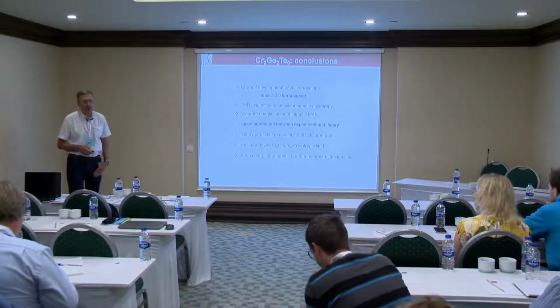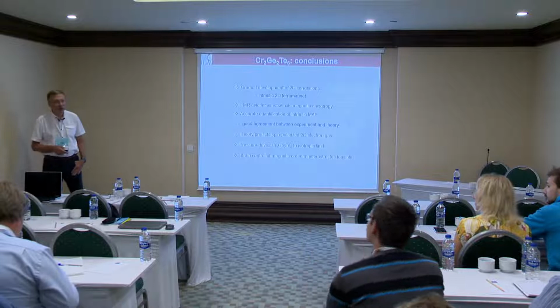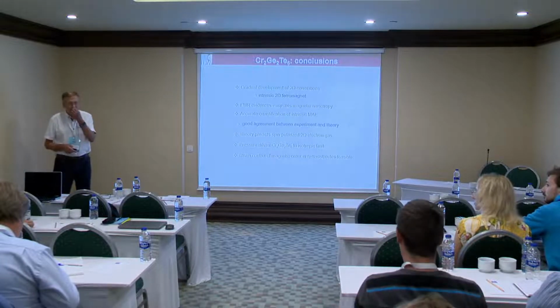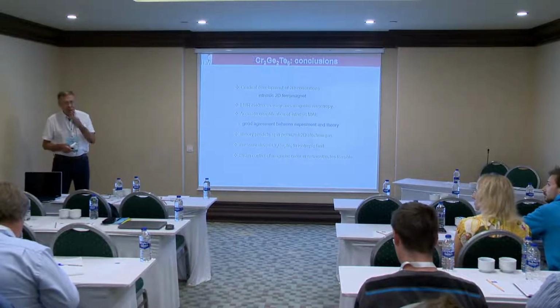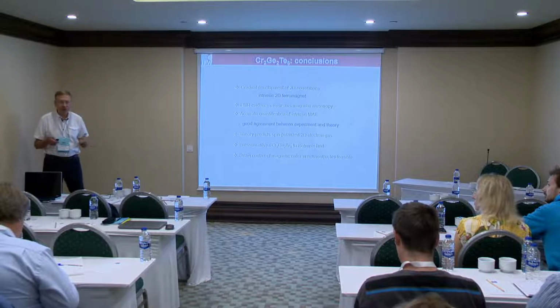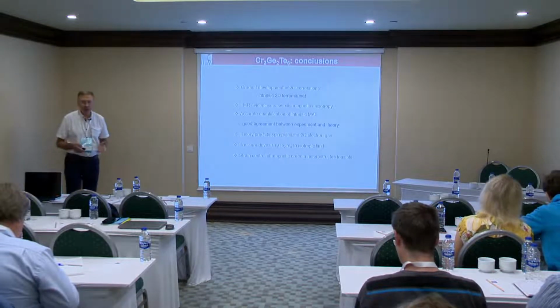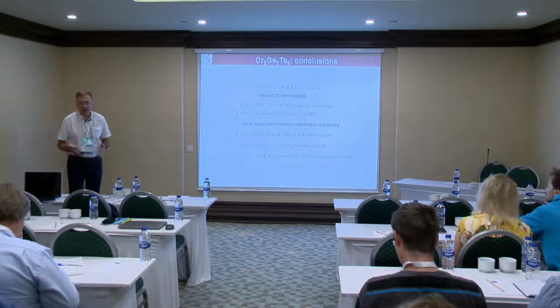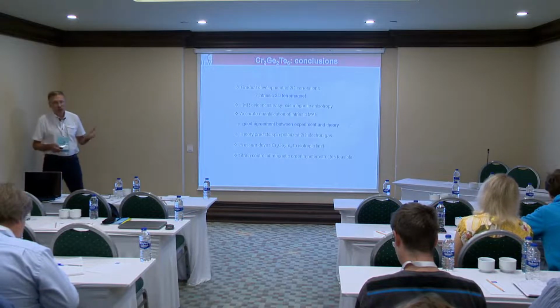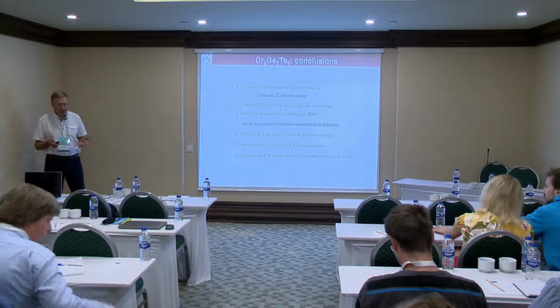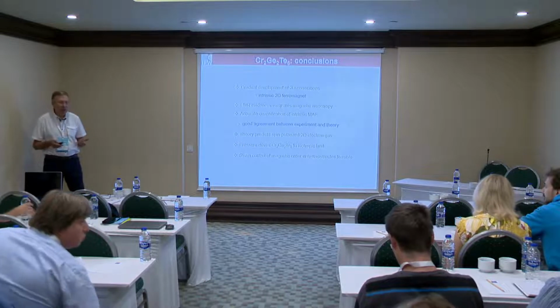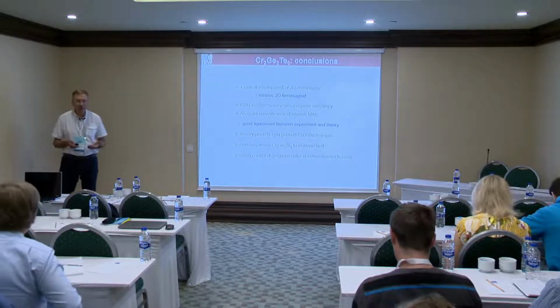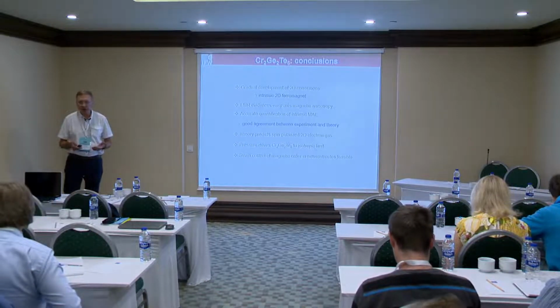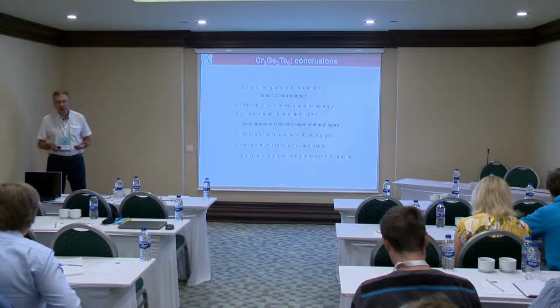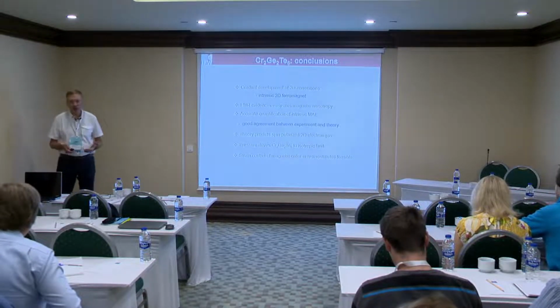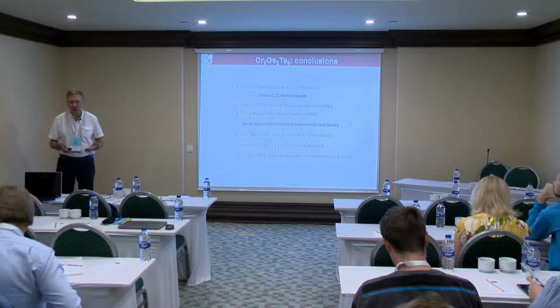Of course, we are not the only ones who are interested in this material. There is a complementary study. First insights into the presence of anisotropy came from static magnetization measurements. But as you have shown, these magnetization curves are very similar for the in-plane and out-of-plane direction because it's a soft ferromagnet. Therefore, to really quantify the anisotropy, you have to look at the spin waves.